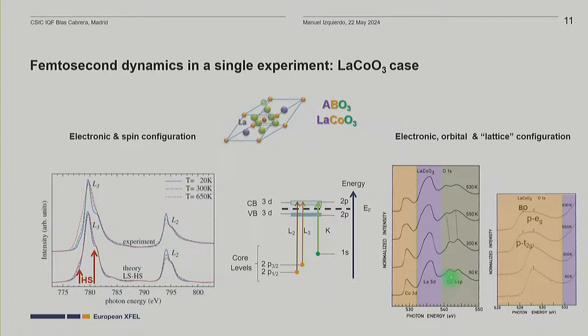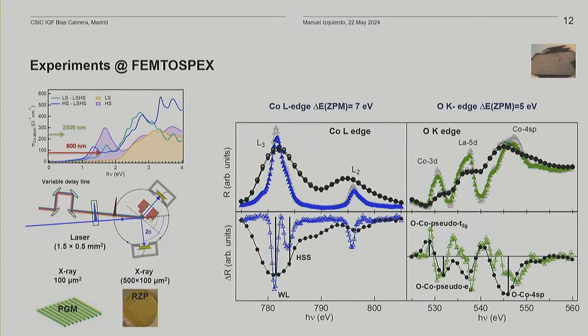And if you study the system as a function of the temperature, you see that you start with fully populated T2G, so this is empty, and as they depopulate, you see here a shoulder that increases. So we did a first experiment with femtoslicing using an 800 nanometer pump, and when you go to femtoslicing, you have to give up on something, because you don't have that many photons, and we gave up on energy resolution.